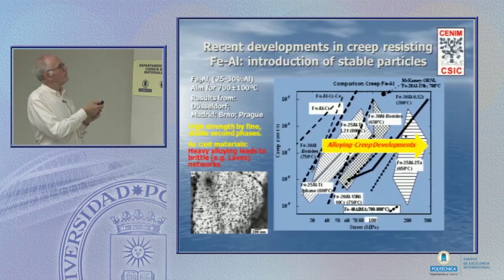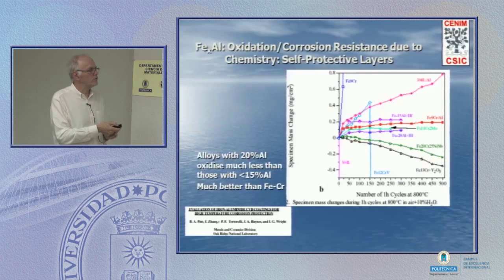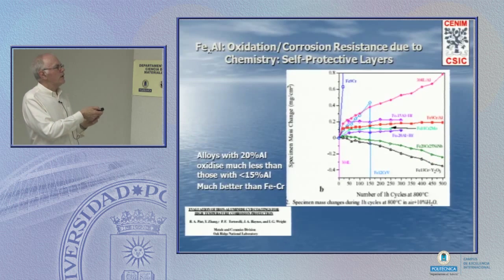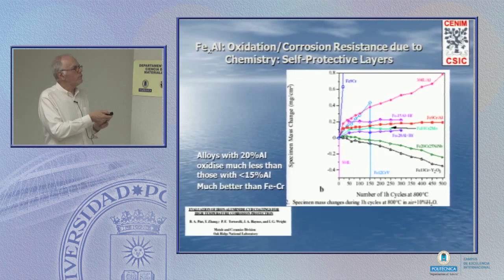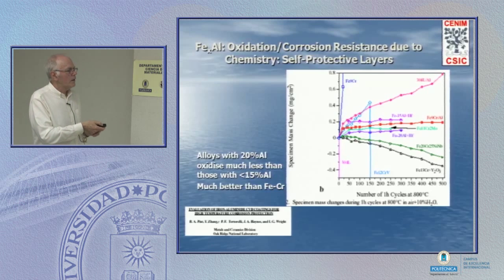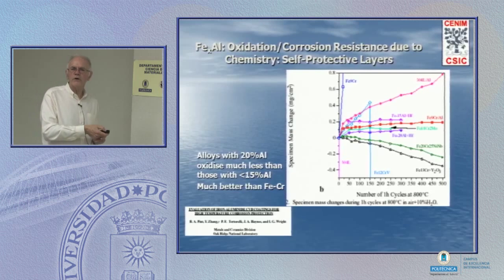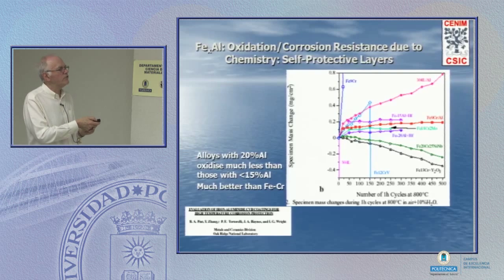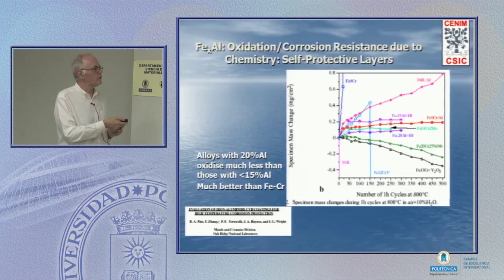Let me say a few words about the oxidation corrosion resistance. Here what we're looking at is the change of weight. If I hold this material, cyclic testing at 800 Celsius. 800 degrees is a very high temperature for a normal chromium steel. Here's iron with 9% chromium. It cannot withstand 800 degrees, and it's oxidizing like mad. It's forming a very thick oxide film. If the film stays stuck on, it still isn't going to protect me. I'm going to consume all the metal.